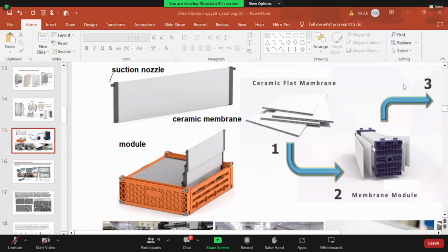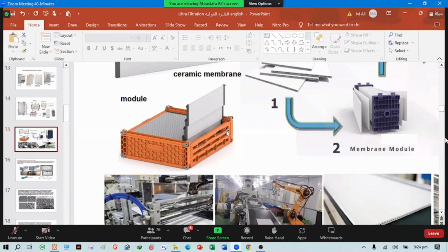Of course, this gluing is done by a wax gun, for heating this wax stick or plastic stick to glue around the ceramic plates and the Noryl plastic parts. The same technique is used also here. We just use a resin to glue the borders of the flat sheet membrane inside the polypropylene. It can be polyethylene, like some manufacturers. So it differs largely, as I say.